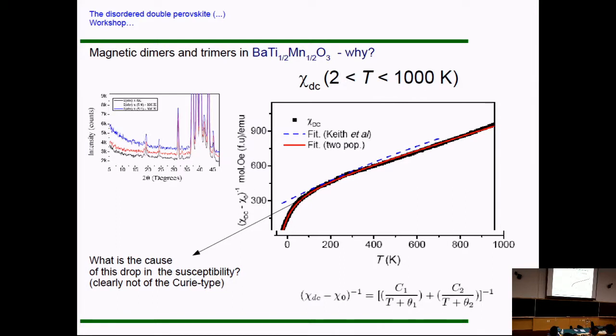And then if you look again at the neutron scattering data at low temperature, you see that you have no additional features here that would appear if you had a magnetically ordered state, right? So you have this drop here in the susceptibility, and here you have no sign of a phase transition. That's pretty much the same with the heat capacity that we had at that moment, and so on.